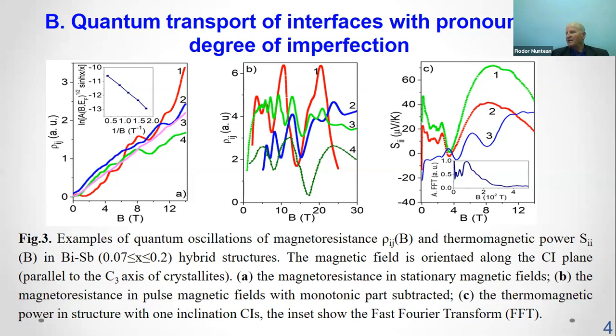This fact reflects firstly a high deformation of the carrier isoenergetics surfaces and secondly a high defect concentration carrying an uncompensated charge. It has been also found that cyclotron masses of Dirac electron and density of state and interfaces layer significantly exceed the respective value for crystallite.